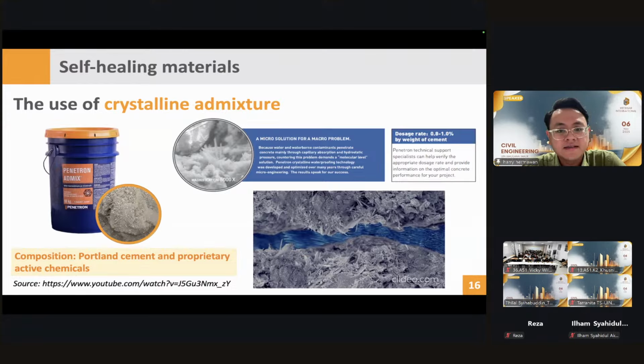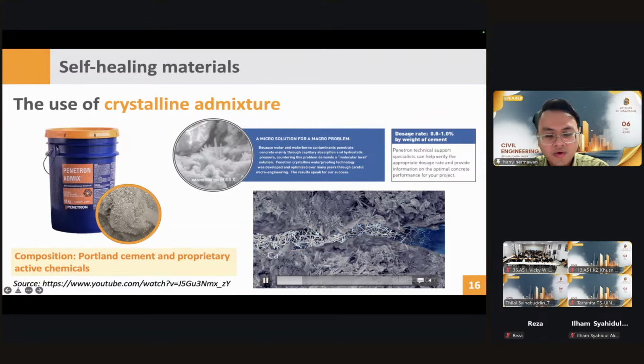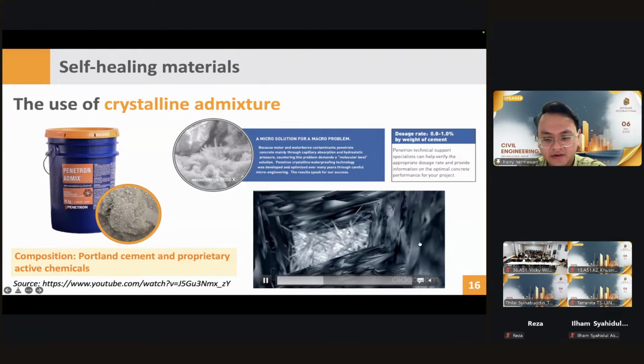Okay, and how this crystalline admixture works for crack healing or for crack closure, here I will also provide another video. So if you look at the video on the bottom here, let's imagine we have a concrete specimen, we crack that specimen, and water comes into the crack. So what's going on in the matrix? With the addition of the crystalline admixture, later there will be some crystals growing inside the crack. And these crystals grow due to what? Due to the reaction with the calcium ions from the cement, and the aluminum ions also derived from the cement, and later it will react with the crystalline admixture to form millions of needle-like crystals inside the crack.